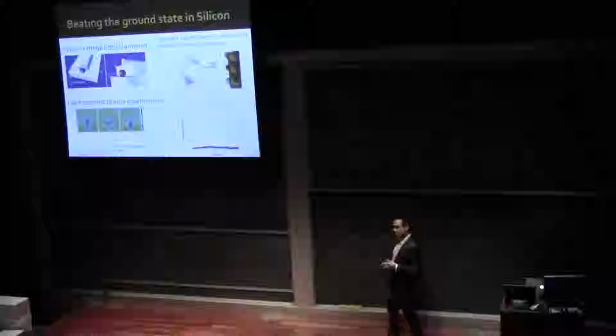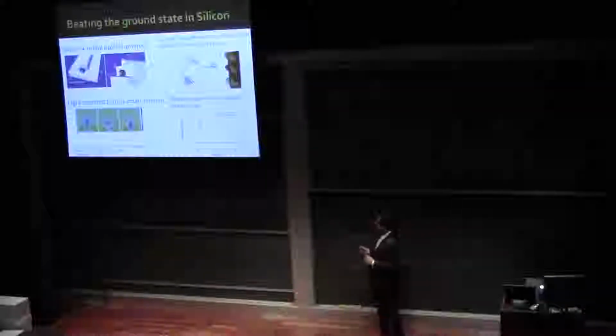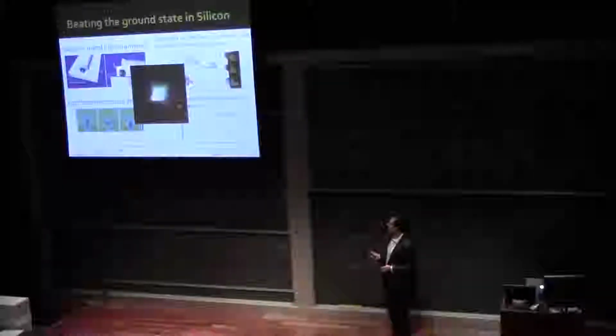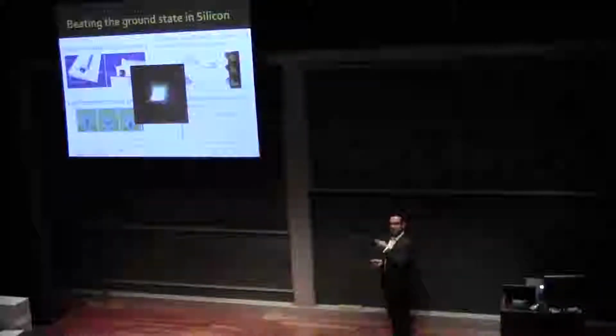So that's the spectrum that I showed you before. Put an optical antenna next to your silicon, and you get this. It's huge. You get broadband emission spanning the visible range. And what does that actually look like? This thing lit up like a light bulb. This is silicon, a light-emitting material.